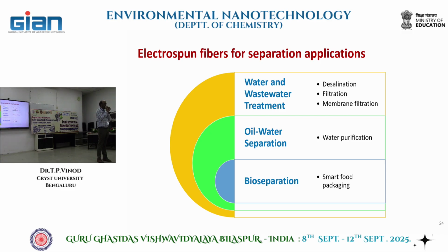And also if you can control the surface chemistry of these fibers, you can make hydrophobic or hydrophilic fibers. If it is a hydrophobic fiber, what will happen? The hydrophobic thing will pass through it very easily, because it has affinity for that. And if you make it hydrophilic, the reverse will happen. So if you have a mixture of oil and water, which is a very serious environmental issue, a lot of oil is being spilled into our water bodies, and how to easily separate it? So if you have a membrane which is custom made like this, and you pour this solution through it, then after filtration, oil only is passing through it, which means oil is separated from water.